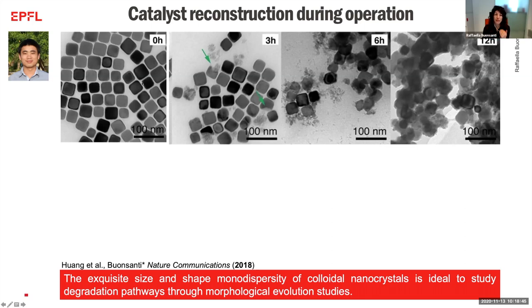Because actually we synthesize this catalyst as perfect cubes, but then we also have to monitor if anything happens during the electrolysis. And the data that I showed you so far were acquired after 1 hour. And in this hour, the cubes are stable. Then my postdoc Zhang Fang monitored how the catalyst changes over time. And what he noticed is that there are clusters detaching from this catalyst. And then eventually they coalesce.